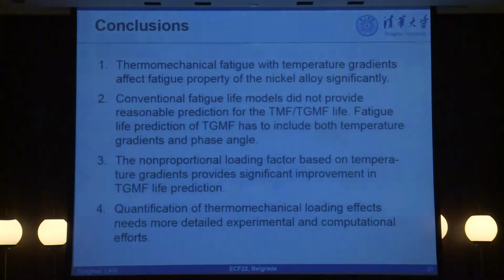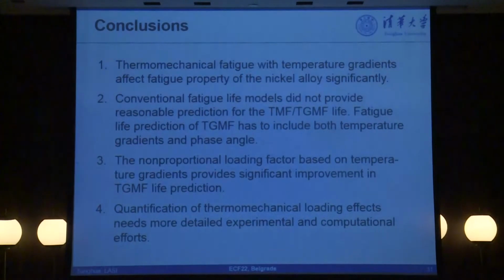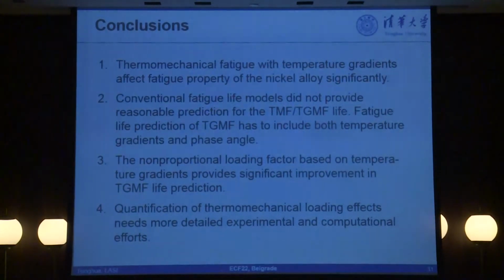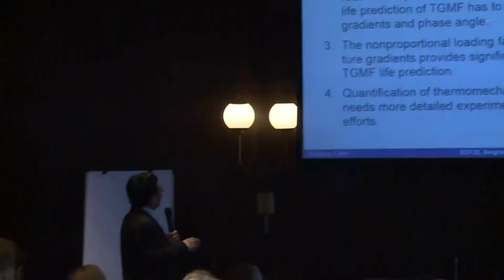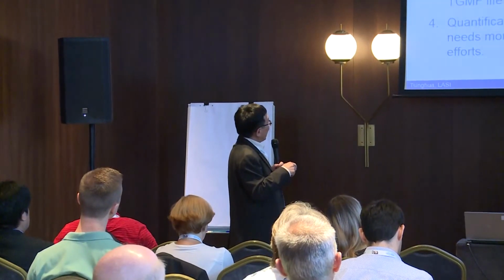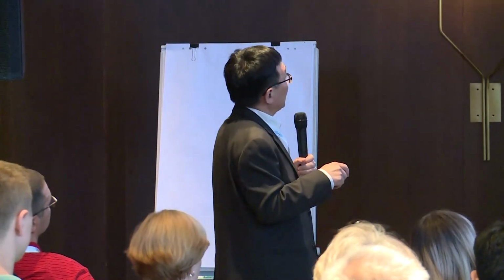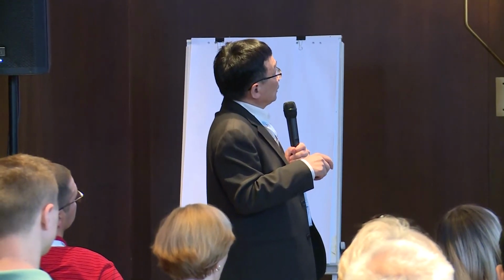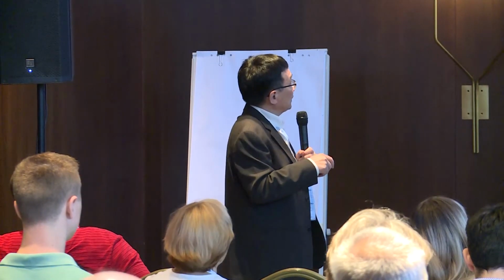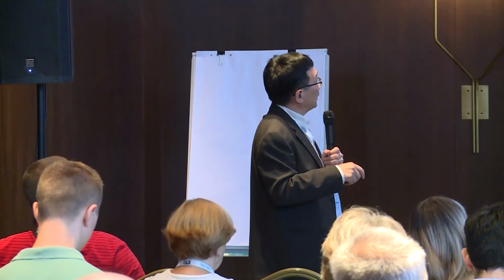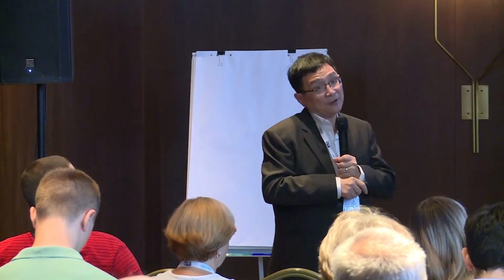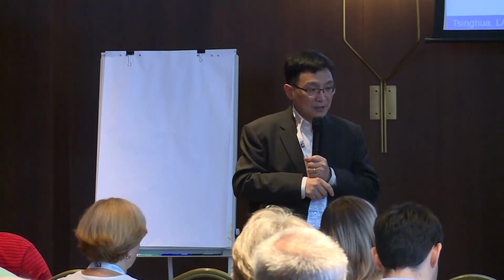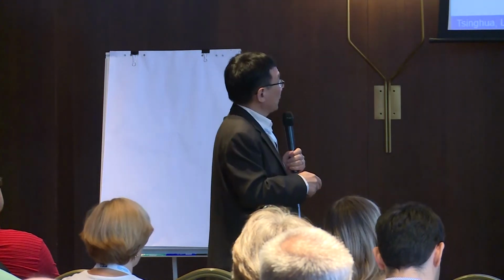Okay, I conclude. Mechanical fatigue with temperature gradients changes material behavior significantly, and the effect of TGMF and TMF has to be considered properly, and the fatigue life prediction of TGMF has to include both temperature gradients and phase angles in the model. That is what we just showed you, and the non-proportional loading factors based on temperature gradients provide significant improvement in the life prediction. The quantification of thermomechanical load effects needs more detailed experiments and combined efforts. The point becomes significant especially for the single crystal case. As I said, the temperature gradient in single crystal becomes higher.